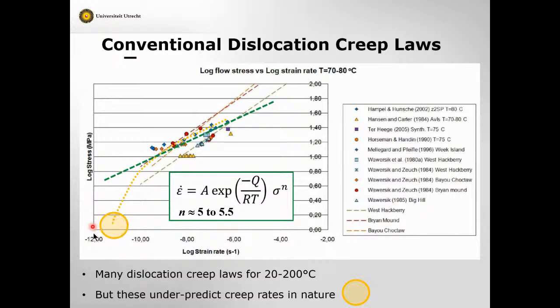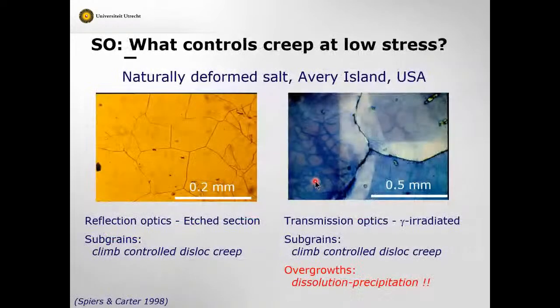That still doesn't explain the strain rates that we actually see in naturally formed salt. So, okay, we have a good description here, but we still are not really getting down to these very low strain rates and very low stresses. We're talking about stresses perhaps below around 5 MPa or something like that, deviatoric stresses. So what does control creep at these low stresses then?